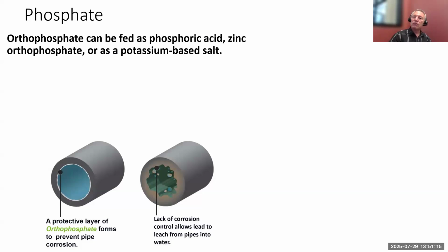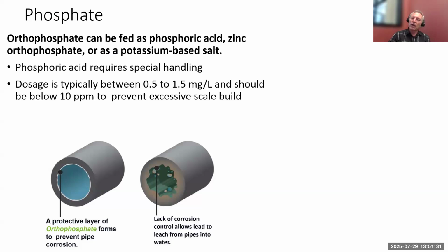It can be fed as phosphoric acid, zinc orthophosphate, or a potassium-based salt. If you use phosphoric acid, that's kind of easy to feed, but it also requires special handling, as phosphoric acid would not be something you'd want to get in your eye, for example. And the dosage is normally between about 0.5 to 1.5, so right around the range that you'd feed chlorine, actually. You want to keep it below 10 parts per million because you don't want to have excessive scale buildup. That can cause just as many problems as it solves.